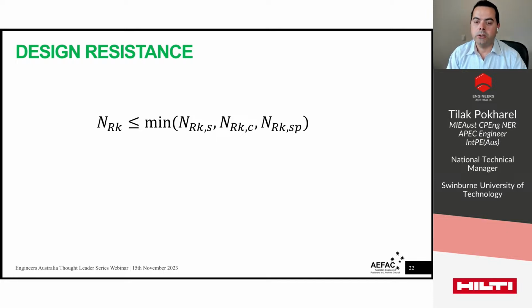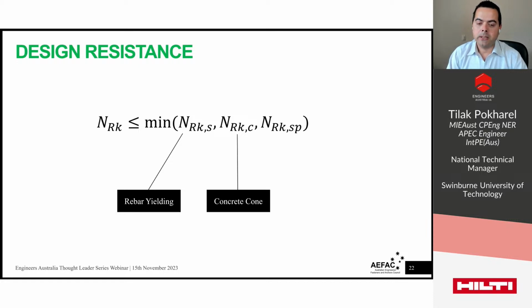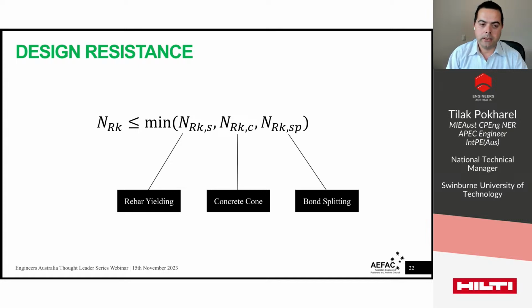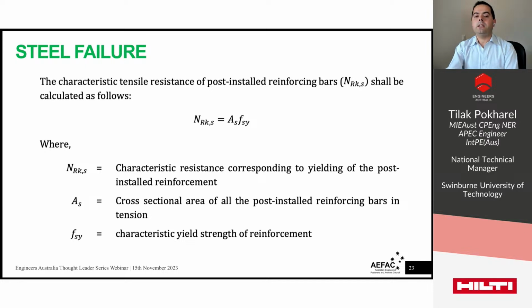Unlike the current rebar model, the new rebar model considers 3 failure modes. The first one is rebar yielding, which is there in the current model as well. Concrete cone, this is not covered by the current rebar model, and bond splitting failure, which is again not covered by the current design model. Okay, the combined pull-out and concrete breakout resistance is also covered in the bond splitting model. That includes some geometric parameters that are not covered in AS5216, such as the small edge distance or the smaller spacing between different rebars, as well as an anchorage length that is higher than 20 times the nominal diameter of the rebar. Okay, 3 failure modes.